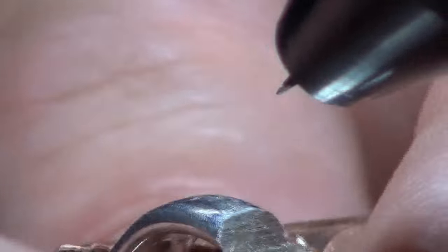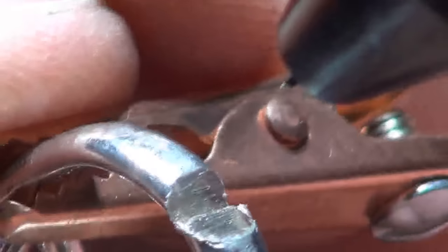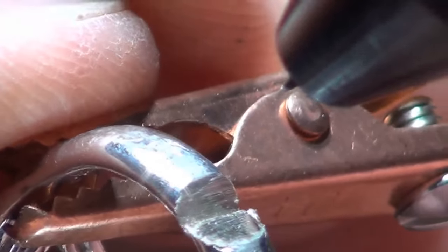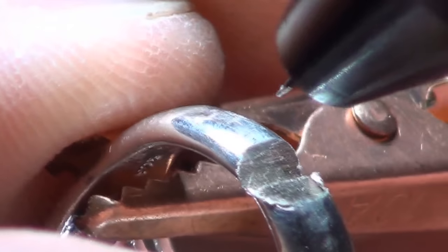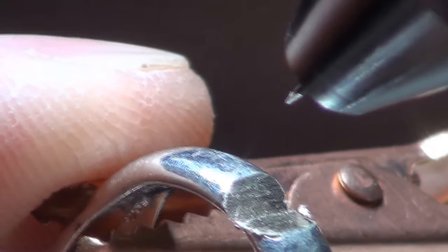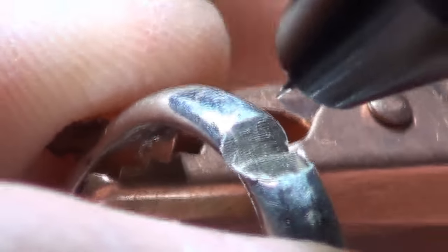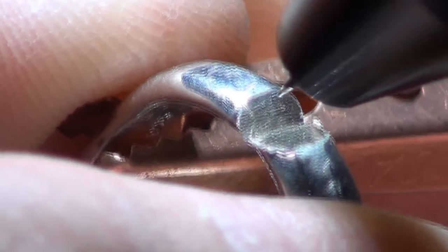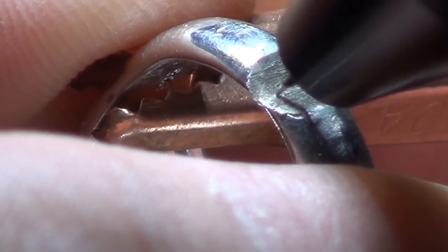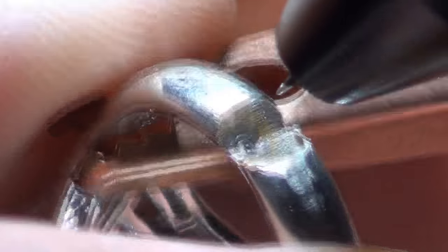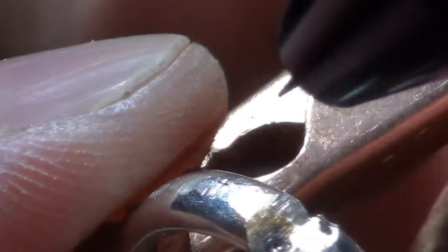We have several different grounding options. But what's important here is we want to make sure we have good pressure pushing the joint together. That will certainly help us to get a better weld, and as well to get that joint tight. So as I press here, I'm going to place a weld right on the edge here, and you can see that. That's just a single weld. You can see that's about what a 30 watt second, 60 millisecond weld is.